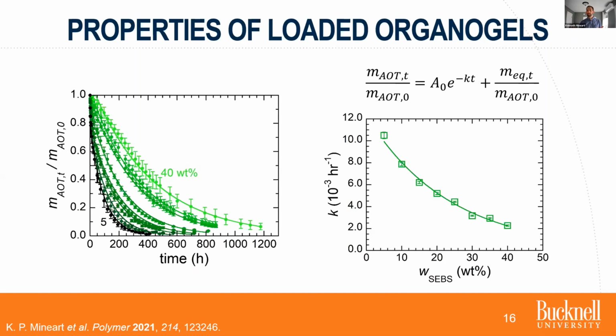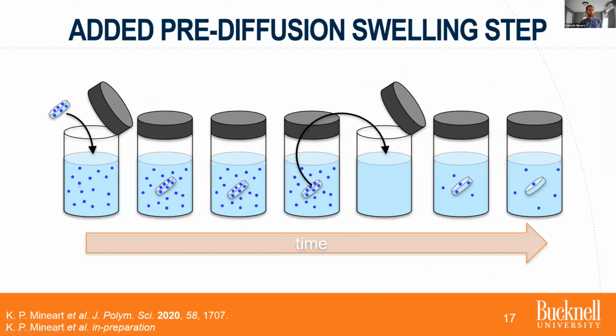And so the next thing we did to move forward and get diffusivity, instead of addressing it theoretically, we went back to the experimental planning board, and we incorporated a new step before our diffusion experiments start. So basically what we do now is we incorporate pre-diffusion experiment swelling into our trials, wherein we take the same gel as before, we submerge it in an AOT surfactant solution of mineral oil at the same exact concentration as the gel.